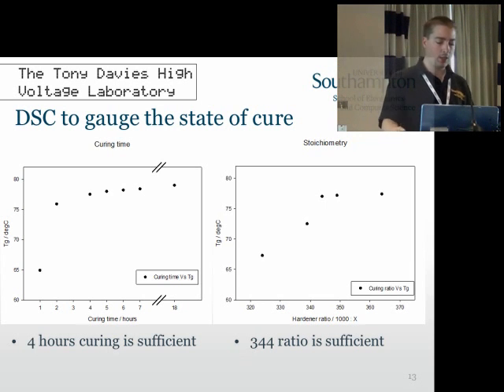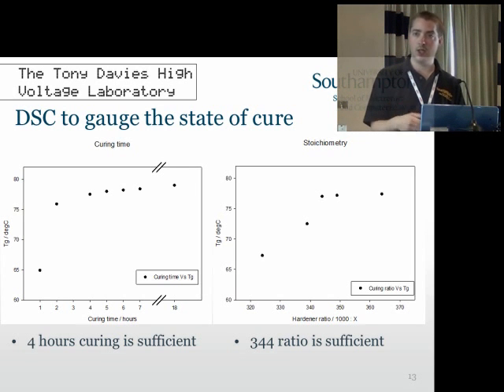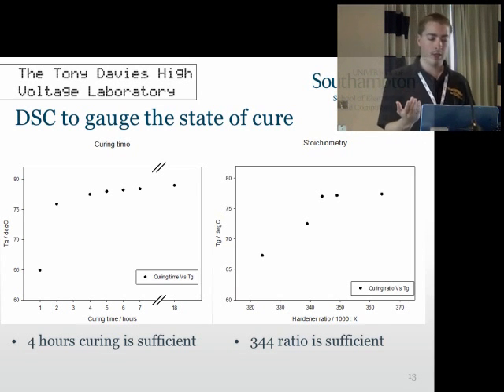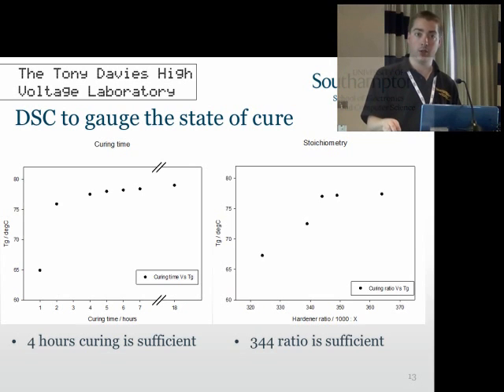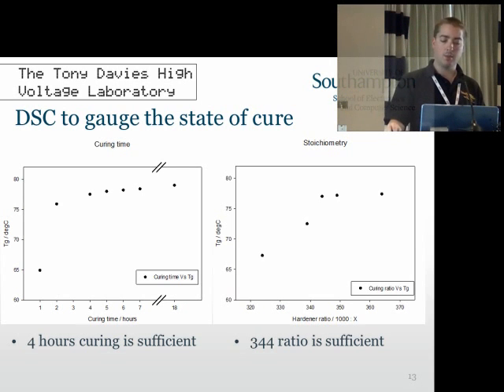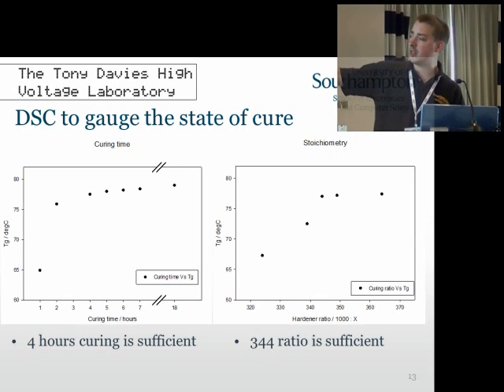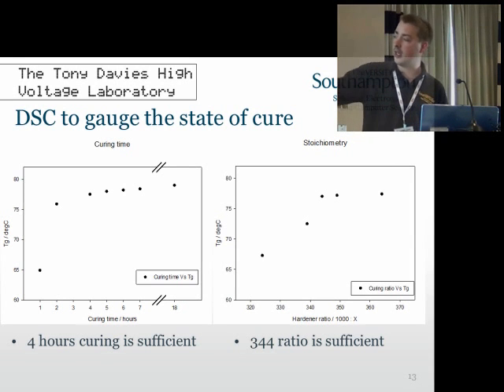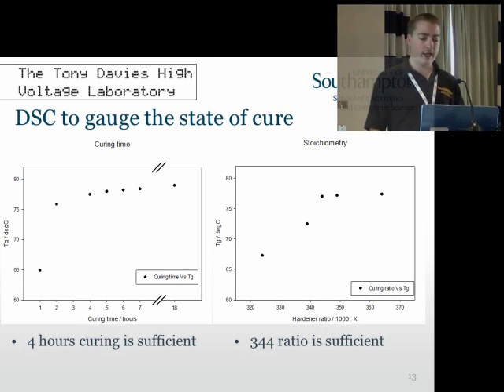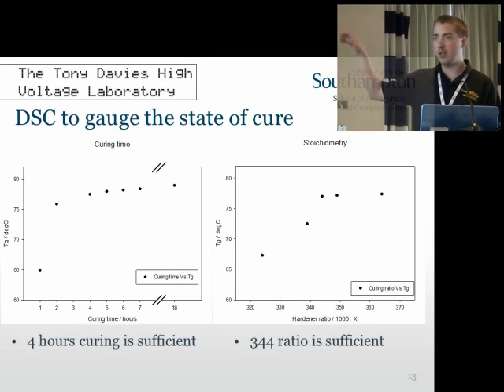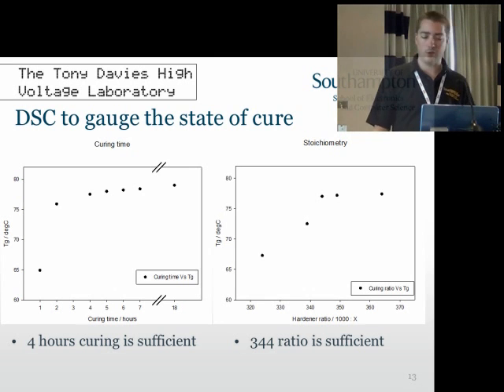Just to establish that obviously the first initial points, the material hasn't fully cured, it's still fairly soft, we've got a low TG, and then at about 4 hours we see that it tails off and starts to level. So we now know that the material is fairly well cured, it's fairly stable. So this is a minimum curing time for us. In the same fashion, on the right hand side, we have the TG on the y-axis and the hardener ratio on the x-axis. Again, increasing up to a point and tailing off, showing that a ratio of 1000 to 344 is the lowest or the minimum that we should consider for this system.